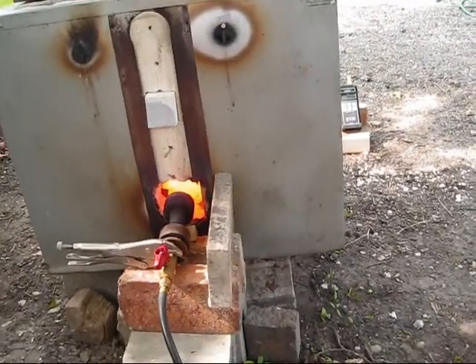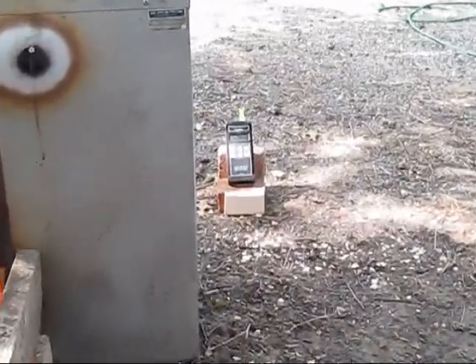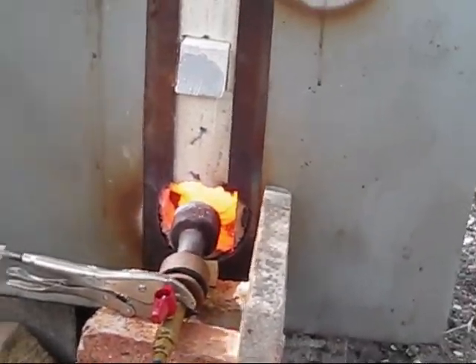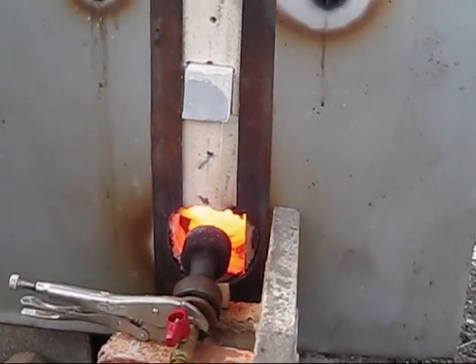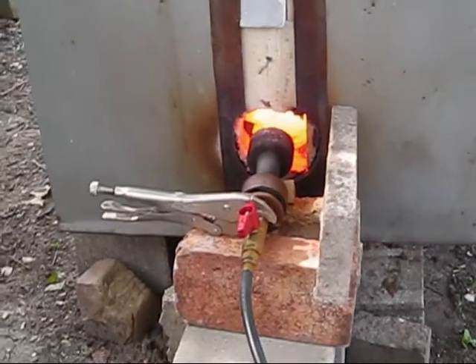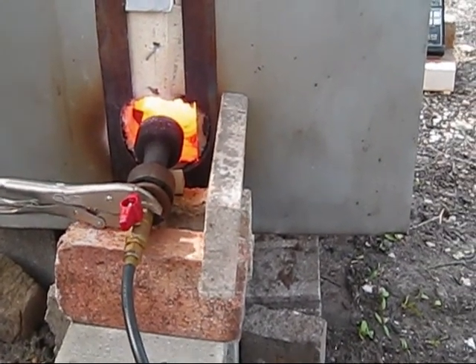We're shooting for 2380. Right now we're at 2241. You can see it from here. So it's been a nice steady climb. We're going from 10 seconds to 20 seconds range per degree. Right now it's probably been exactly four hours. So I would say within the next hour we're looking done.